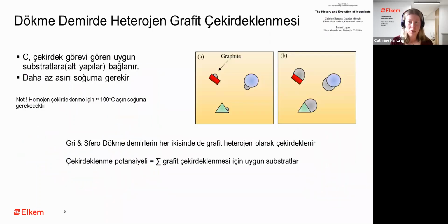Now, the nucleation of graphite in cast iron will be heterogeneous, as it requires less undercooling. With the temperature window indicated in the slide before, which was 5 degrees, but with the chemistry you will have a window of around 20, 40, maybe up to 60 degrees. It is not feasible to have homogeneous nucleation, because homogeneous nucleation typically requires more than 100 degrees undercooling before it can start. So both gray and ductile iron rely on heterogeneous nucleation of graphite. During heterogeneous nucleation, the graphite nucleates and grows from a foreign substrate. This process requires less undercooling and is in line with the observation from thermal analysis and microscopy data that shows that you do have solidification taking place at a higher temperature and lower undercooling than 100 degrees, and you don't have a lot of